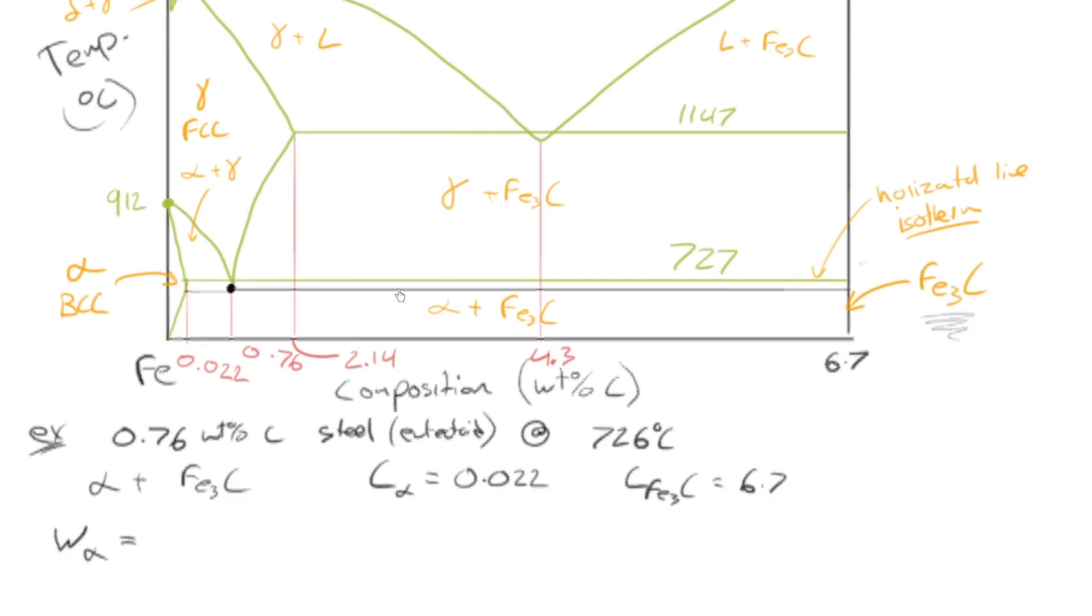we must take the opposite side of the lever. That is, we must take this side here divided by the total. This dot is closer to the alpha phase, so intuitively you know there has to be more alpha. So if you ever look down on your page and it doesn't make intuitive sense, you've not got more of a phase that you know there should be more of,